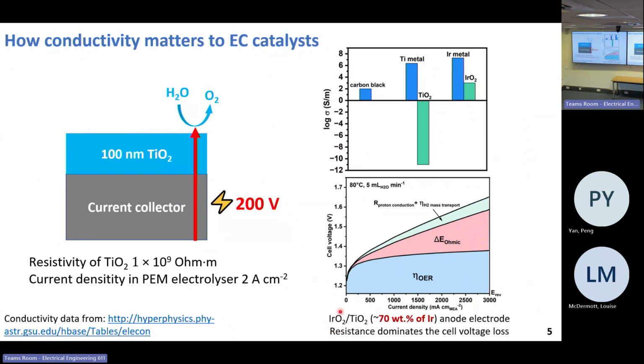Commercially available iridium oxide, titanium oxide catalyst still requires 70% iridium loading to sustain the activity and conductivity of the catalyst layer. And when we put them into a PEM electrolyzer, the ohmic drop takes up a significant part of the overall cell voltage loss.